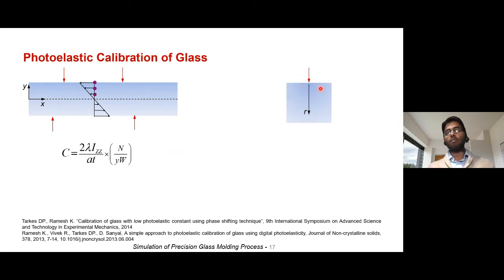This was a special type of setup where the force is acting at a particular point, and near to this point you can expect that the stress is going to be very high. So then it would induce some photoelastic effect. This was also done for special types of glasses, and for LB2000 glass, which had relatively high photoelastic constant, we were able to measure it more accurately. And similarly, for very low photoelastic constant glass, which has a value of 0.042, we were able to measure it precisely by using the 6-step phase shifting technique.